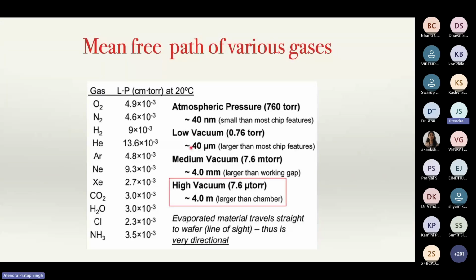So at 0.76 torr, which you call low vacuum, the mean free path becomes 40 micrometers, and for 7.6 millitorr it becomes 4 millimeters. For high vacuum, which normally we work at, like 7.6 microtorr, something like 10 raised to power minus 6 torr, the mean free path is 4 meters.